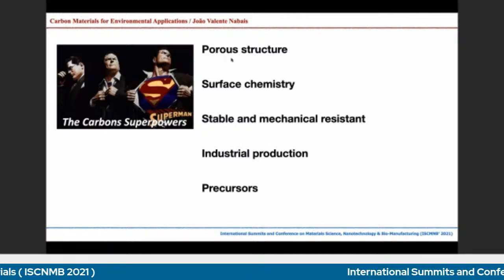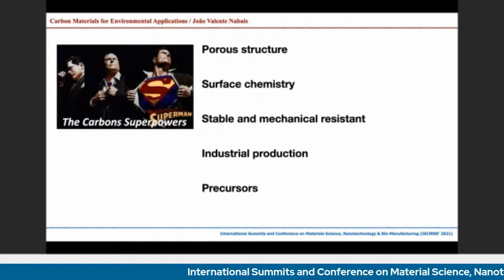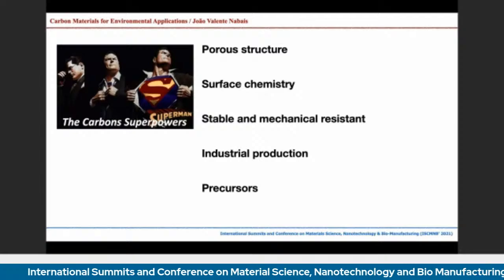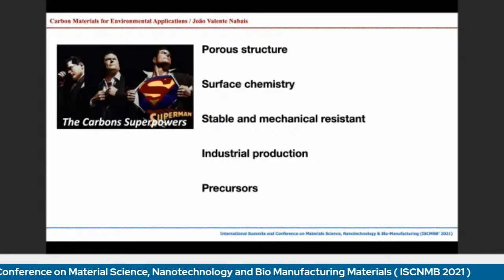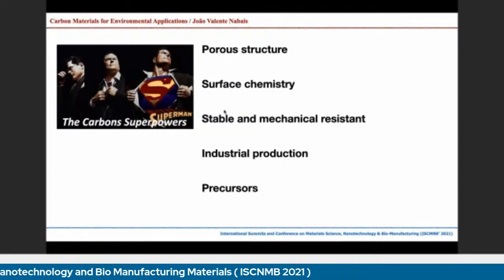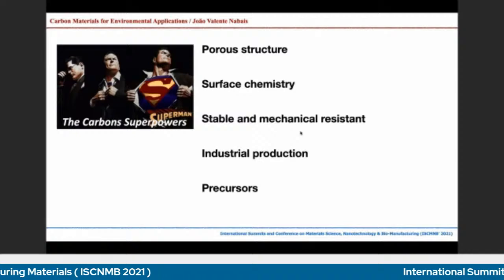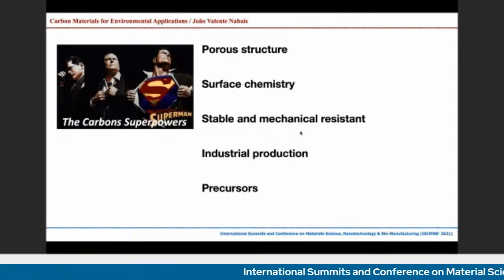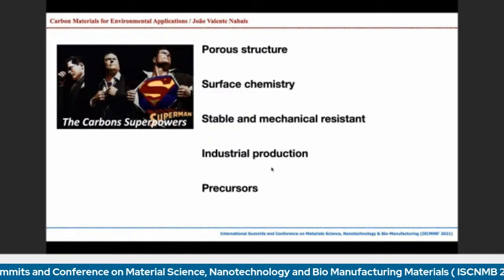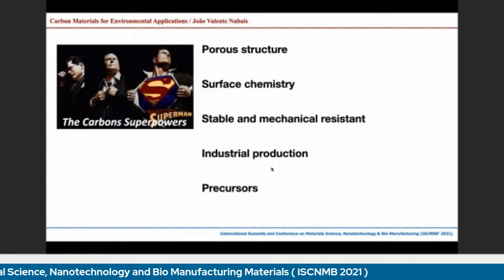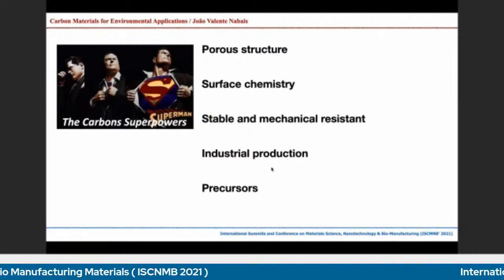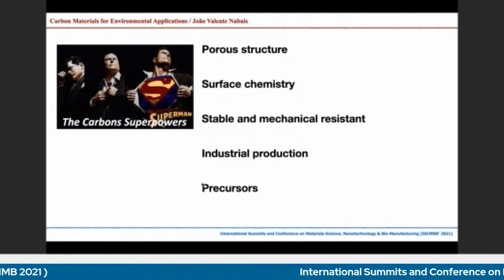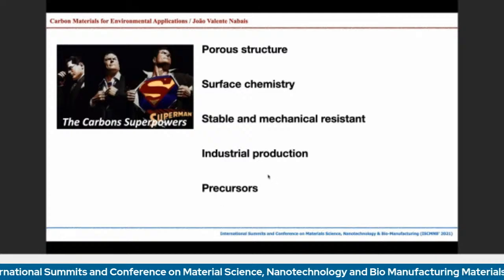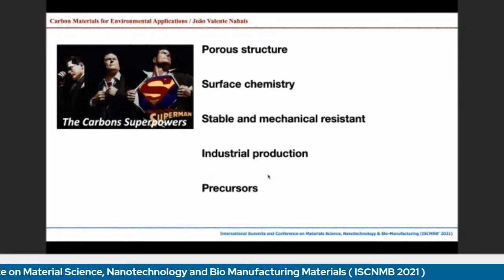Allied with this porous structure, we have a very rich surface chemistry, which also promotes the adsorption, and not only adsorption but also acting as a catalyst, for instance, in some reactions. They are very stable and mechanically resistant, which is quite important for specific applications as well. The industrial production is very well known, and these carbon materials have been produced for many, many years now. So we have very well established industrial production methods. And we can also use a lot of precursors to produce activated carbons. This is quite important because we can use wastes, for instance, as I'm going to show a little bit later.